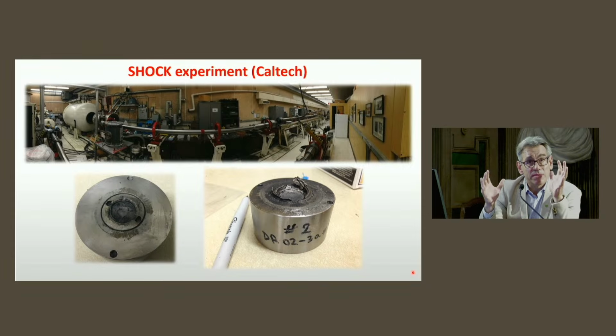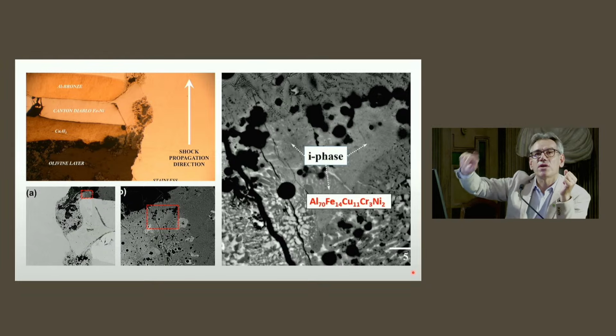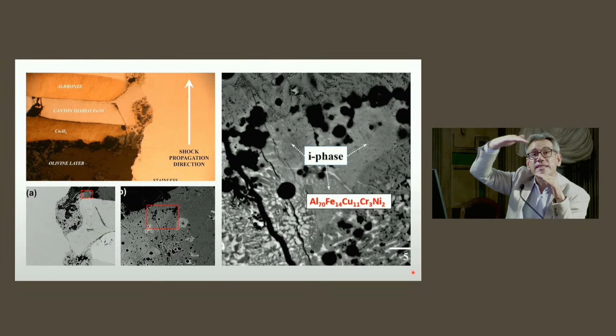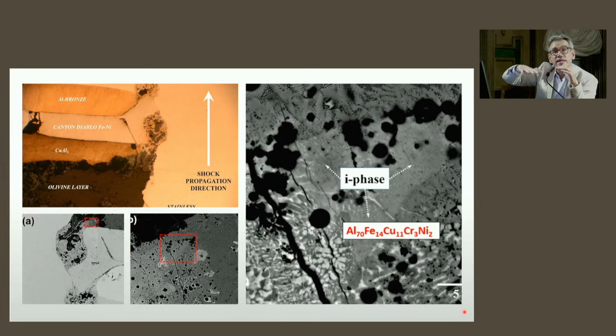We spent months designing the possible experiments, which is tremendously expensive. In the end, we decided to use, as you can see at the top left of the slide, four different disks stuck together: an olivine disk with a composition exactly identical to that observed in our meteorite, then a piece of copper-aluminum alloy, then a piece of Canyon Diablo iron-nickel meteorite, a very famous metallic meteorite, and then a piece of commercial aluminum bronze. Everything was stuck together and put in the stainless steel chamber.